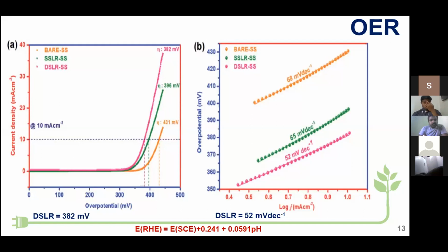Using this and extrapolating the kinetically controlled region, we can determine the Tafel slope, which is depicted in figure B. Again, among these three, the double side laser irradiated stainless steel exhibits a low Tafel slope of about 52 millivolt per decade. Here, the potential scales are converted into the RHE scale, that is the reversible hydrogen electrode scale. Why? Because all other reference electrodes are pH dependent, while the reversible hydrogen electrode is independent of pH. That's why we are expressing it in terms of the RHE scale.